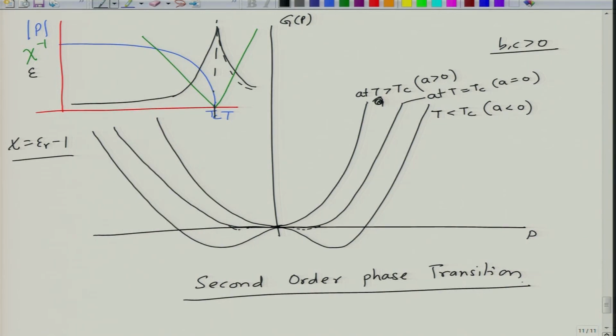phase transition. And if you calculate in this case, you will not have a discontinuity in entropy or specific heat when you calculate for these materials. So, these are second order continuous phase transitions where susceptibility does not change abruptly at the transition, and the order parameter, polarization is called the order parameter, does not abruptly become equal to 0, rather it goes to 0 gradually.